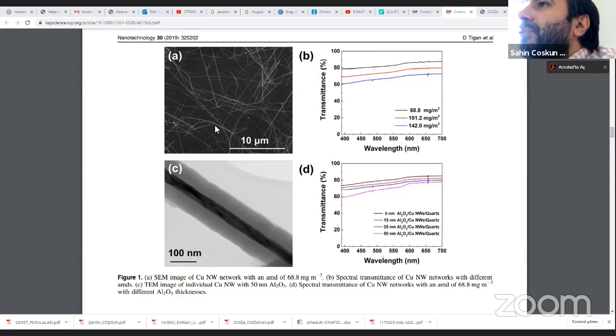So have you had a chance to check such rough materials, rough thin films actually, or did you get any feedback from Bruker users on the crystallinity check of those materials? Well, I think this might not be very much different from what I've shown here. What is the substrate? Are they deposited on a single crystal substrate? Silicon substrates are generally preferred, actually. First, copper nanowires can be coated as a 2D network structure, and then atomic layer deposition is applied to form a conformal coating.